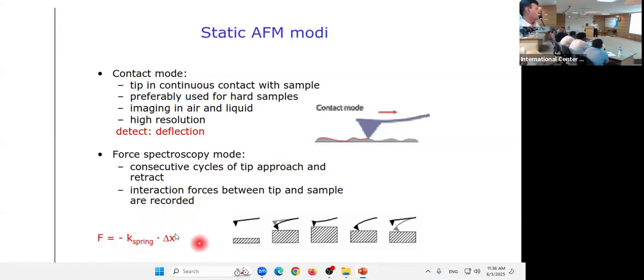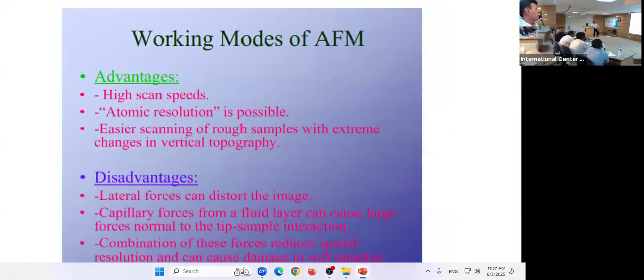So here, in the contact mode, as you can see, when it comes to the surface, at the different surface, the cantilever deflection is different, and this deflection you can see in the deflection of the laser light, because the laser light would also deflect in a different pattern here. That is one. This is what I discussed. The advantage, as I just mentioned, is that atomic resolution is possible with the contact mode. It will give you much better resolution.